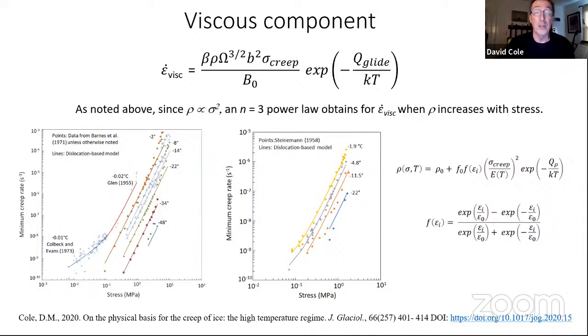The 2020 paper I mentioned, this is quick results here. This really focused on the creep component. It was targeted for the glaciological community. So the ice mechanic community can basically ignore anything over about minus 1.8 because we don't have sea ice there. But this is just to let you know that over a fairly wide range of applied stresses and temperature, the creep component does a pretty decent job of capturing observed behavior.